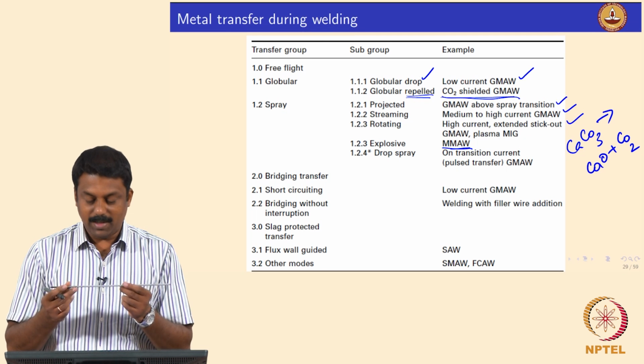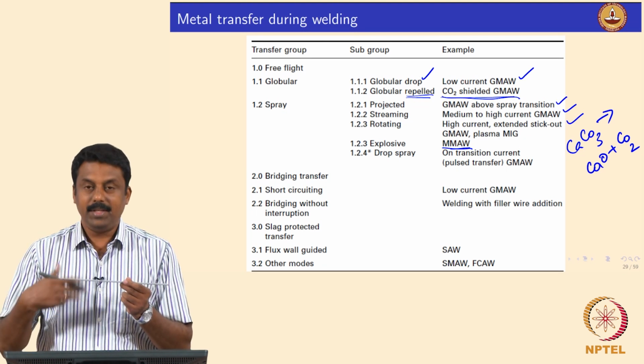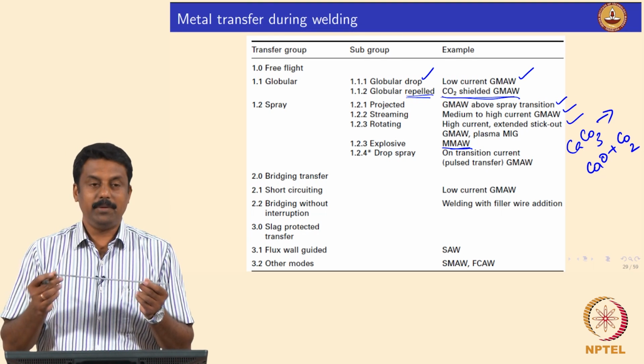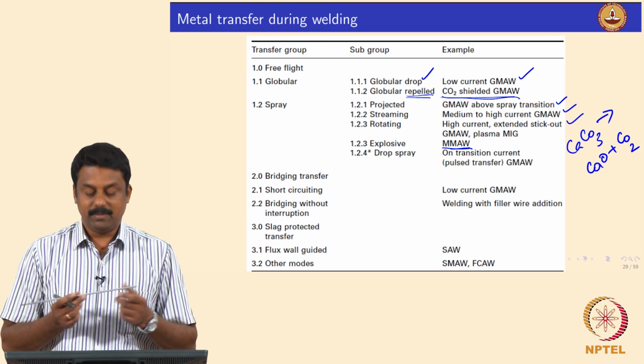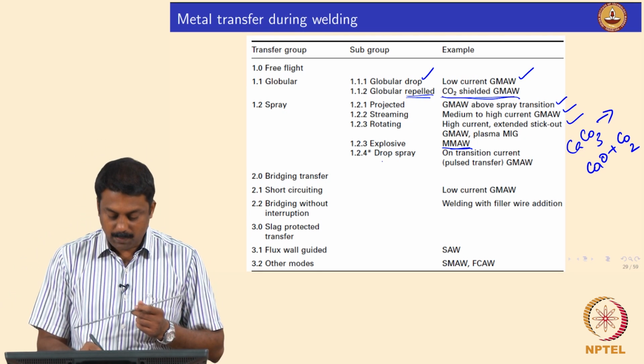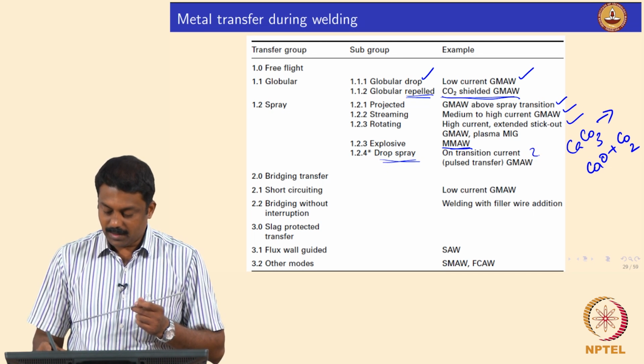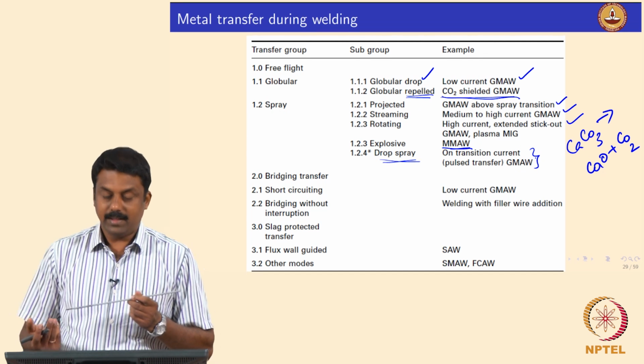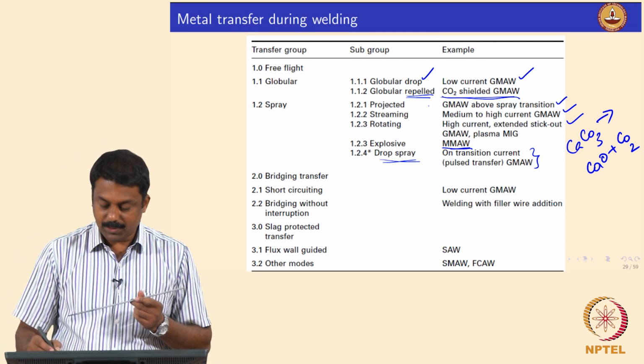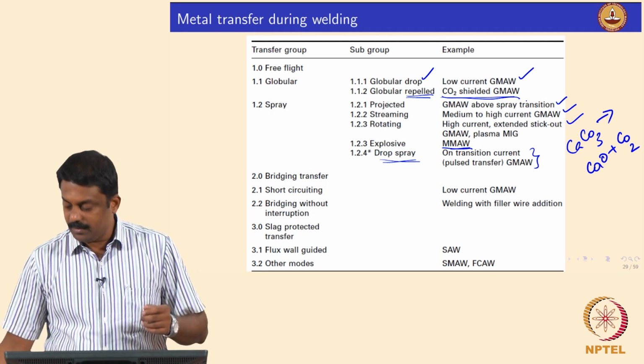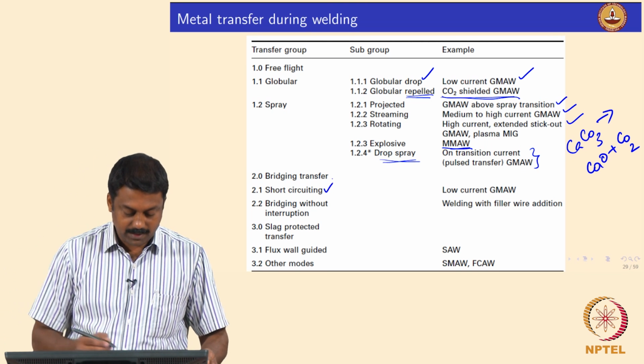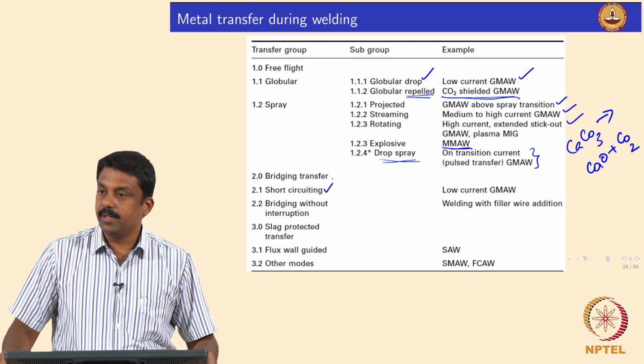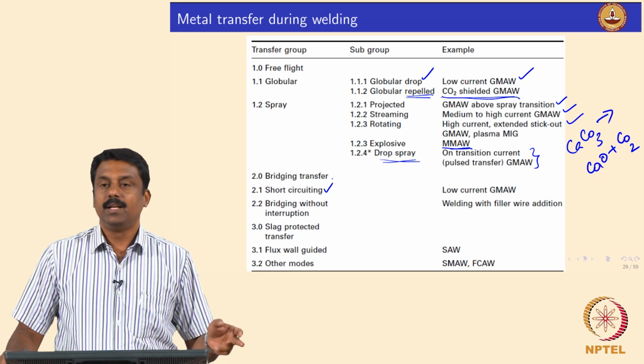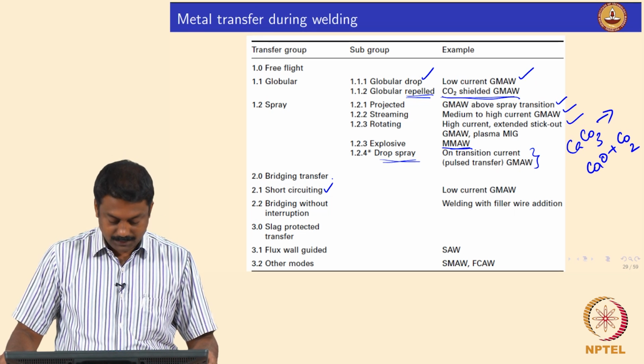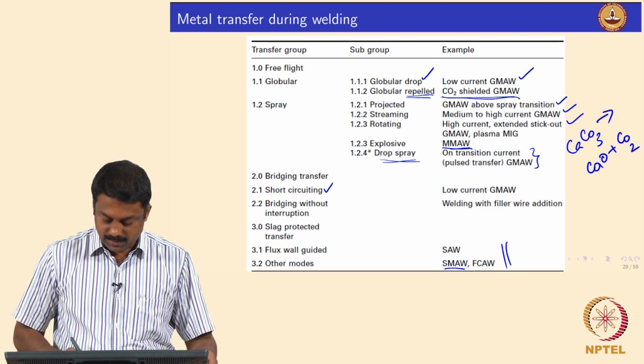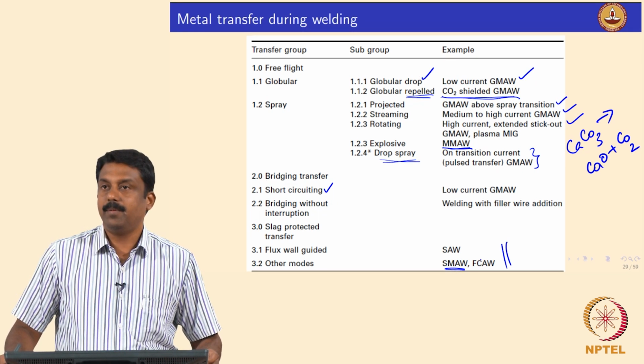This is used for metal arc welding or shielded metal arc welding, and because of the CO2 generation plus the high current you use to melt such a large diameter electrode, you sometimes get an explosive transfer. Drop spray, just above or around the spray transition, is the most advisable transfer mode, drop spray or the projected spray. So, those are the various transfers you would see. You can also achieve the short circuiting transfer by carefully playing around with GMAW parameters like wire feed rate, voltage and current. Other modes you will see when we look at the mechanisms of SMAW and FCAW.